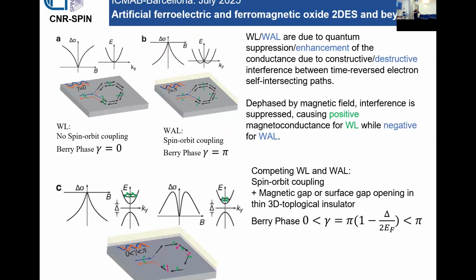This is very well studied, in many materials, and works very well also for oxides. You can fit the data very well when this situation applies. But if you have a non-trivial Berry phase, which depends, in our case, on the magnetic gap, the magnetoconductance has a completely different shape, because it's a competition, in the same range of magnetic field, of weak localization and weak anti-localization terms. It is a consequence of the opening of the gap at the Dirac-like point. And I have to underline that this kind of physics has been developed in the case of topological insulators with the magnetic gap or with the gap at the Dirac point.